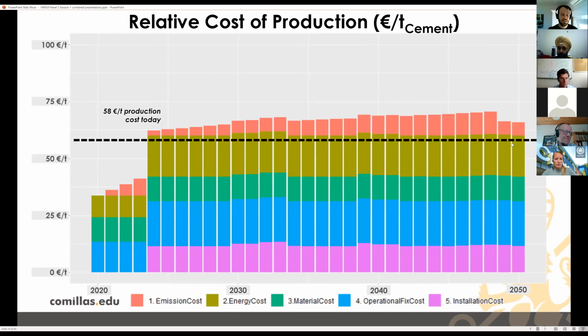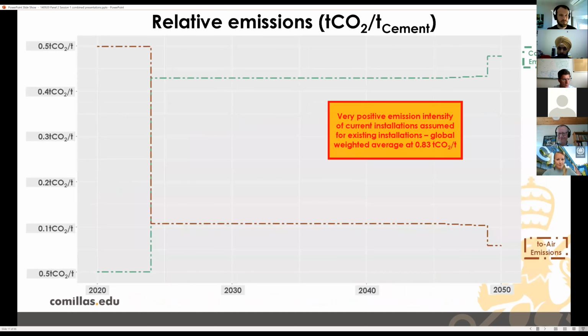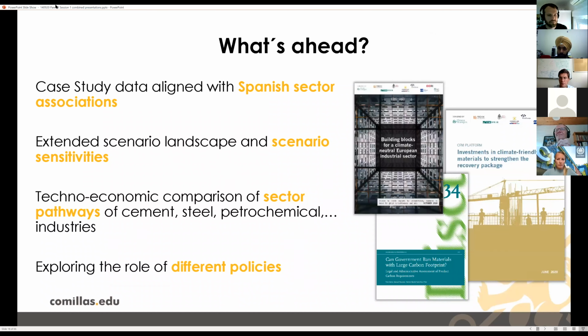It only gets a bit lower if you install integrated CCS, which is then, the model actually runs until 2100, compensated by the annualized cost. If we look at emission reduction, again, in the model we have a very positive assumption about the emission reduction of 0.5 ton CO2 per ton of cement in the end. You can basically reduce emissions because the max capture rate that you have is 90%, leaving 10% of the original one. So where do we go from here?